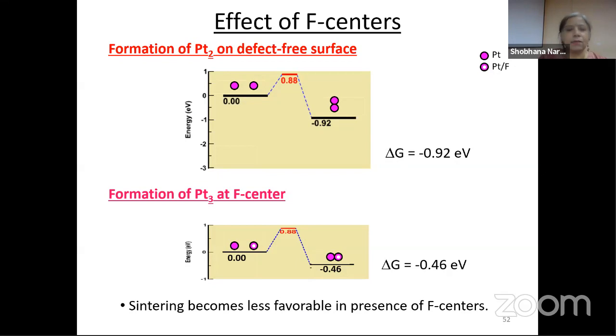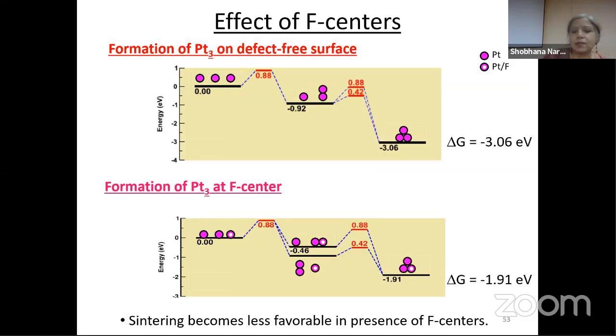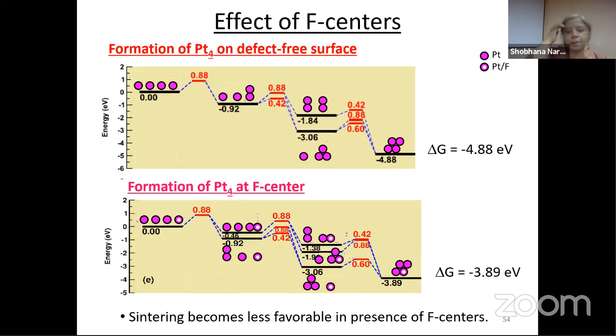We can also look at the effect of defects. Okay, so sintering becomes less favorable when you have defects, which is what you would intuitively expect. And this is true for all sizes. But again, it is for a counterintuitive reason. Because the diffusion barriers are the same, but there are clusters that are being pinned at these defects. And then the lowering of energy when you join a defect is a thermodynamic rather than a kinetic reason, which is disfavoring sintering when you have defects.